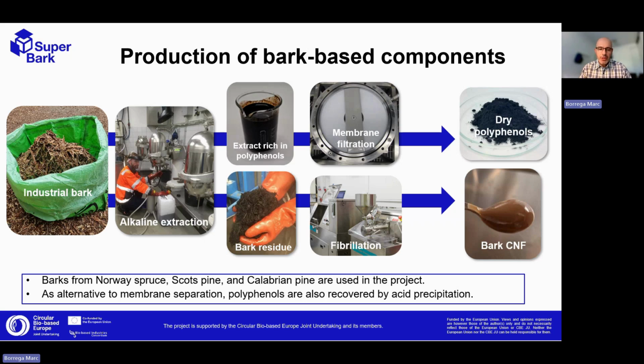Then the bark residue, which is enriched in cellulose, is fibrillated, and you can produce this type of hydrogel, which we call nanocellulose. And since we still have lignin and residual polyphenols in the bark residues, you can see that the bark-based nanocellulose still has this brownish color.